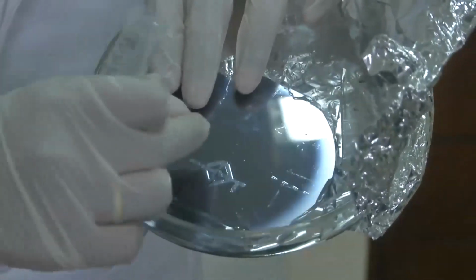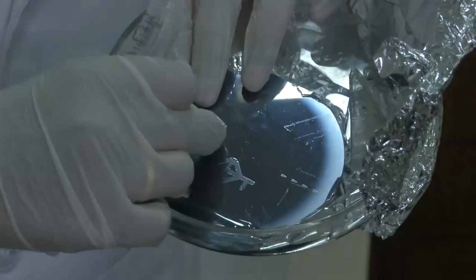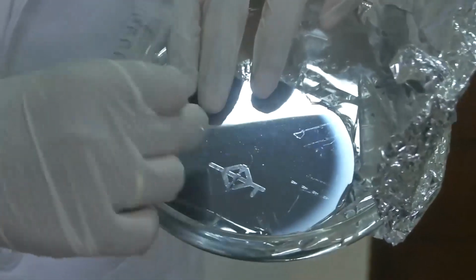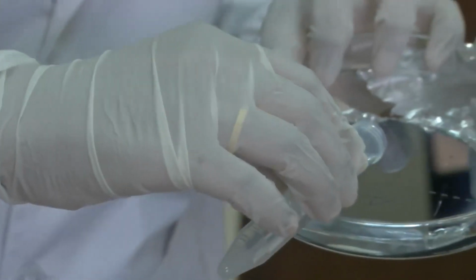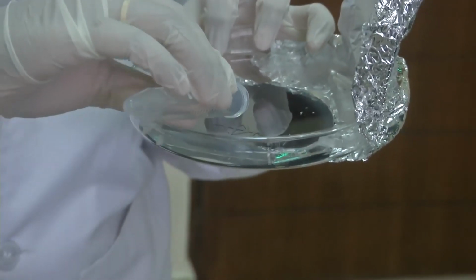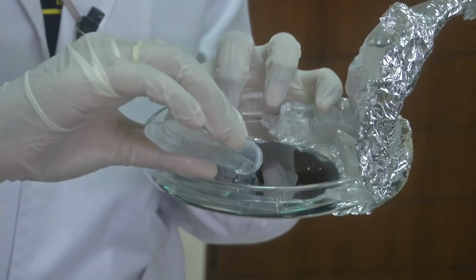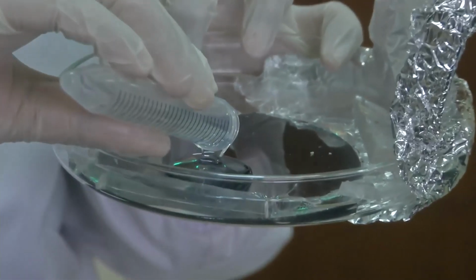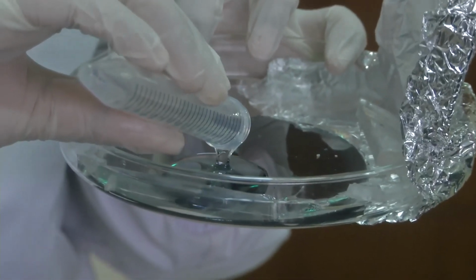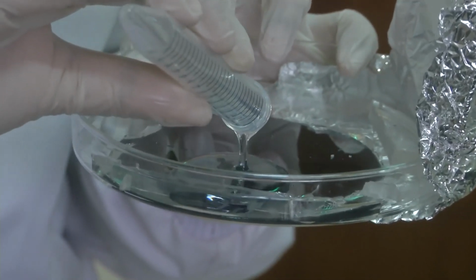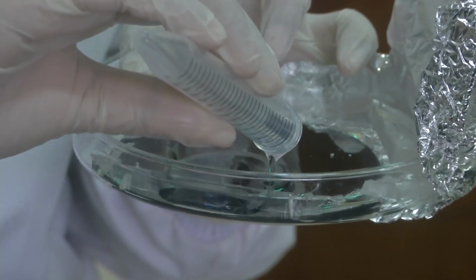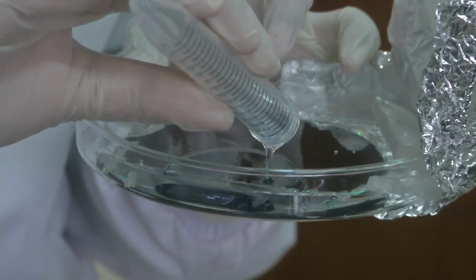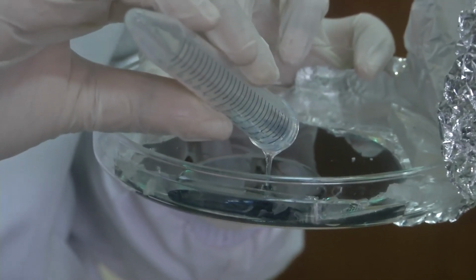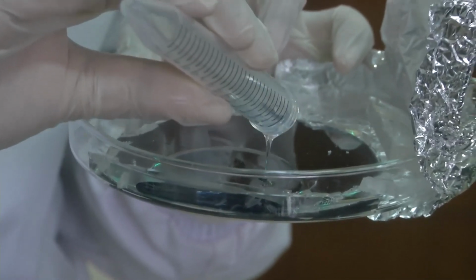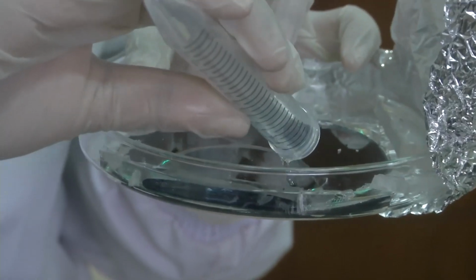If you want micro channels in your MEMS based device, the BioMEMS device, then you could just have the micro channels engraved on this. Once I have this PDMS layer, I would pour it onto this mixture, keeping it very close to the surface, because when you pour it from a very far distance, it would tend to create bubbles on top of it. There is a very small amount of polymer mixture that I have taken, depending on the dimensions of your device. So, you could choose the quantity that would be more appropriate to get the device.